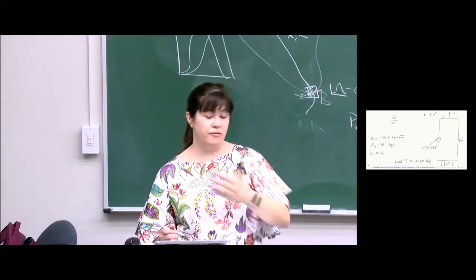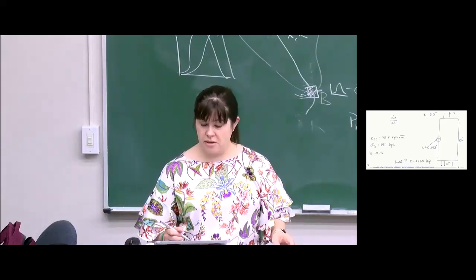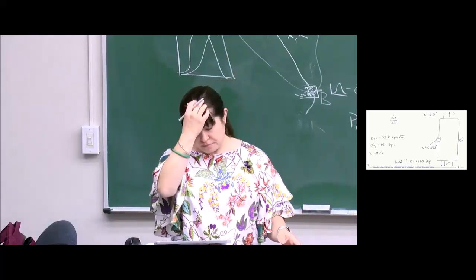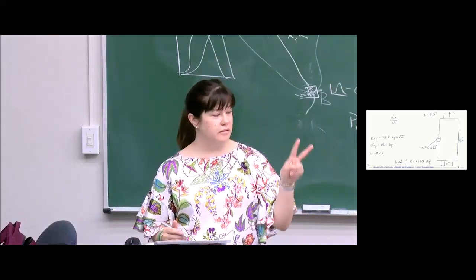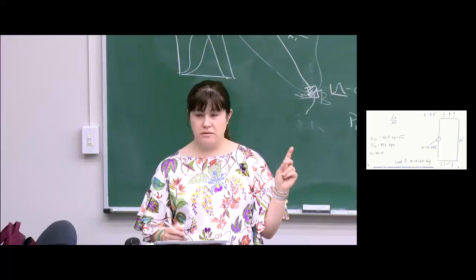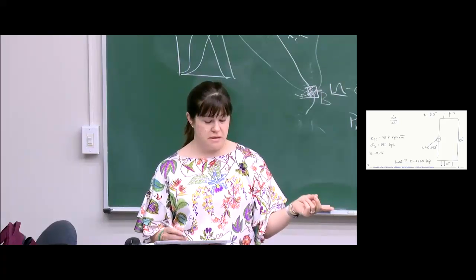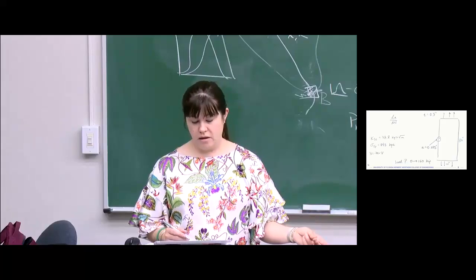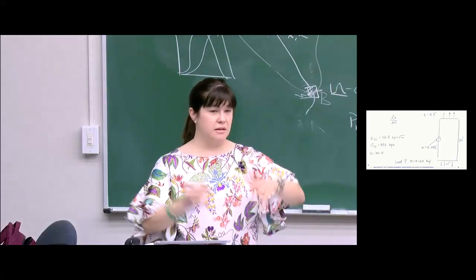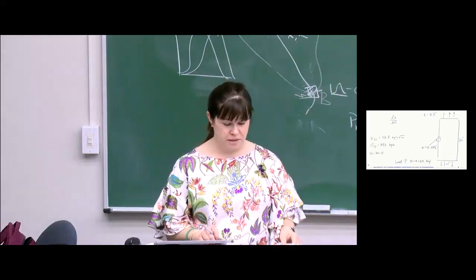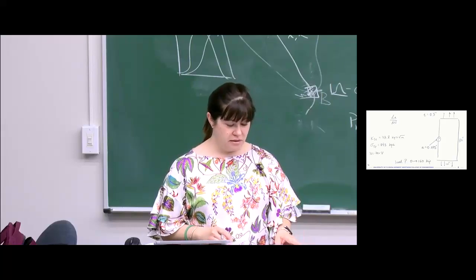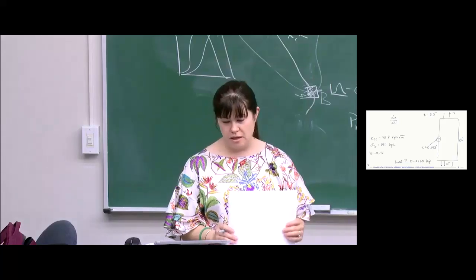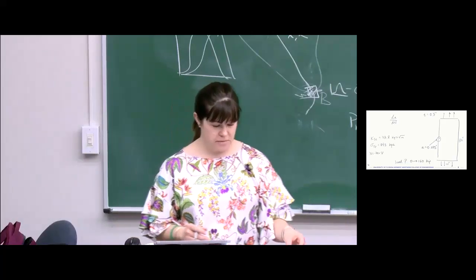So we're past the phase of cumulative damage. Is this going to get a crack in it? It's already got a crack. So therefore, we're only left with two possibilities. One, that there's stable crack growth, right, da/dN, and there's some slope to that plot we'll use. Or this crack is already big enough that it's expected to have catastrophic failure already. Okay, but that would mean the estimate of remaining life is like 0, right? So if they tell us we're to calculate remaining life, there's probably some life remaining.